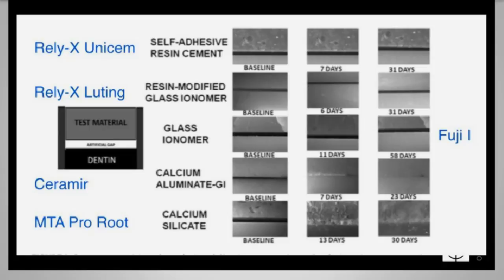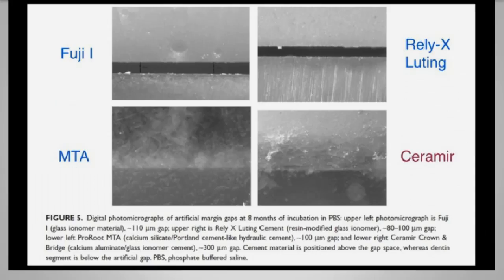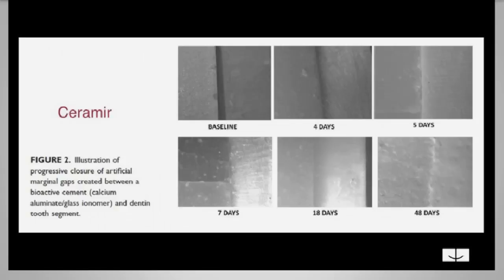If you look here, baseline, 7 days, 31 days, of course that gap isn't being filled by the self-adhesive resin cement. But with the bioactive cements, at 7 days, you already had crystalline formation. At 23 days, 30 days, look at that. Unbelievable. I'm going to show you another image here. Oh, let me go back here. Here's Ceramir, right? For Ceramir alone, here's baseline. Look at that gap. 4 days, 5 days, 18 days, 48 days. Look at that. I just couldn't believe what I saw, that you can actually occlude an artificial gap with this cement.